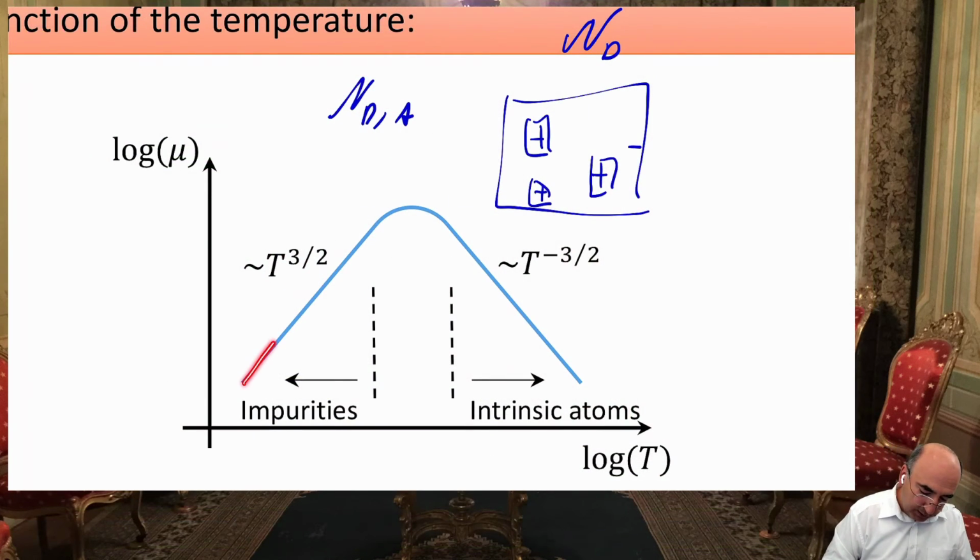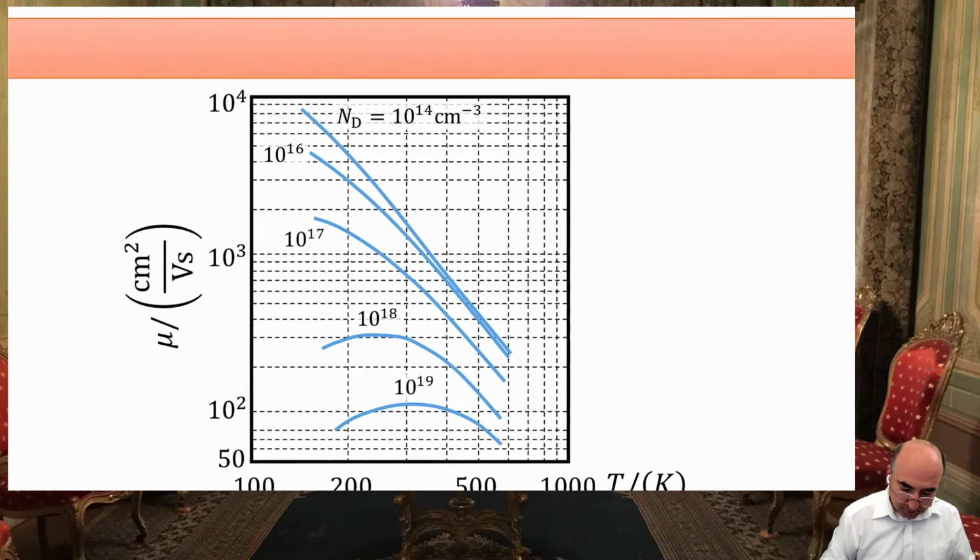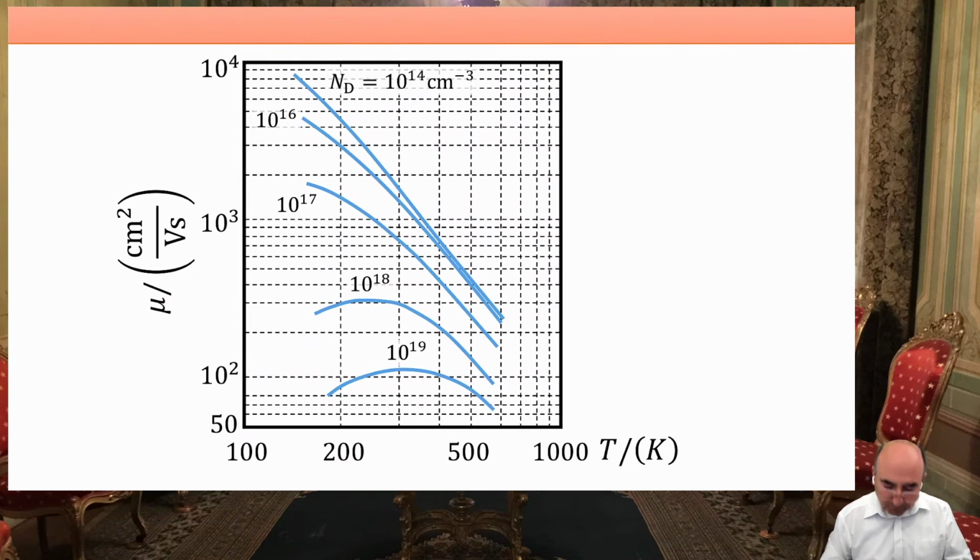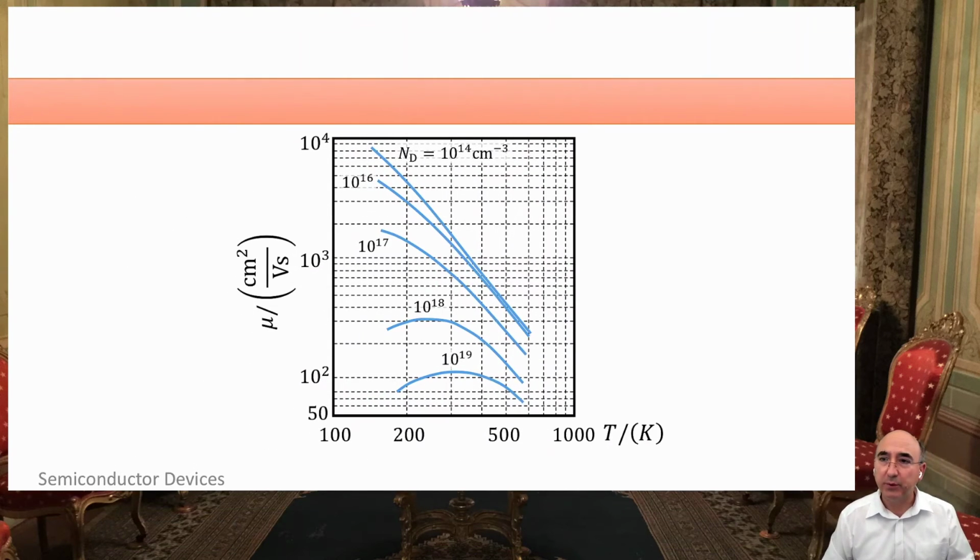In my lecture notes, it is just this sketch and this sketch. If you have the book by Mauro Zambuto, you have these curves also there. From Mauro Zambuto, I have this picture. So low doping, I have only lattice scattering. High doping, I have the increase in the mobility due to the reduced effect of the impurities and the expected lattice scattering effect, which is dominating here.